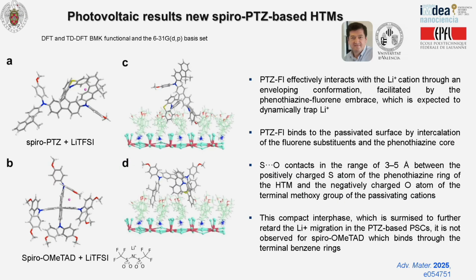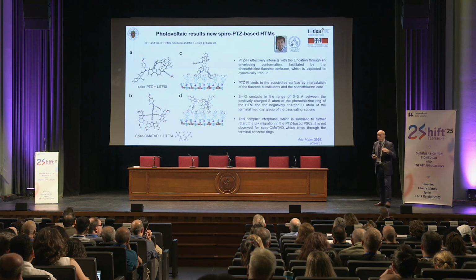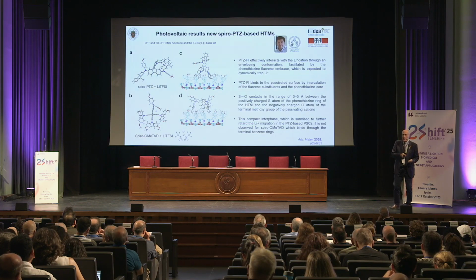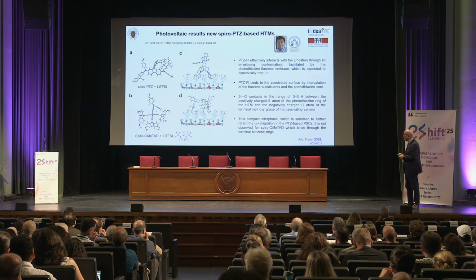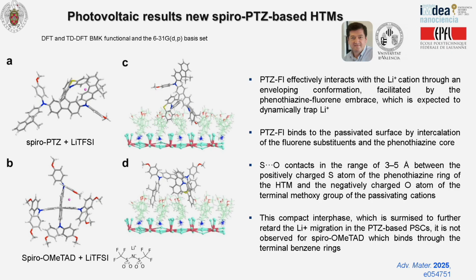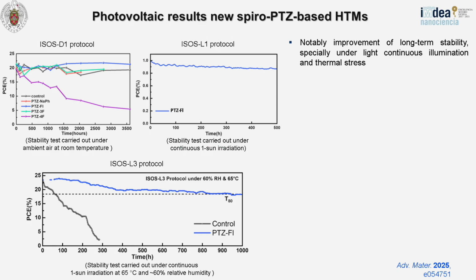Anyway, in order to account for these results, Enrique carried out interesting theoretical calculations. Without spoiling his results, simply to say that the idea is that the lithium in this compound is retained, is complexed in some way with the aromatic part, in contrast to the other one, the spiro-MeOTAD. And that means that the lithium is one of the drawbacks for the stability of this system. So the lithium is retained and doesn't go to the perovskite, okay? That would be the conclusion for this study.